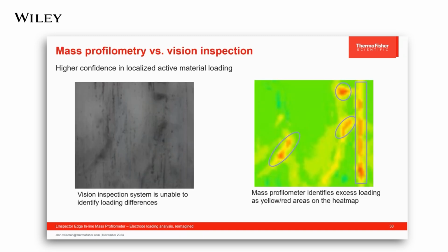The example on this slide is a good way to consider the difference between optical inspection and mass profilometry. The image from an optical inspection system on the left looks at the surface of the electrode, and in this case, the algorithm did not flag any abnormality. Mass profilometry mapping of the same sample shows clearly that the darker areas are actually areas where the loading is too high, indicated in red. Additionally, the vertical streak of high loading is clearly identifiable in the mass profilometer data, while it is completely invisible to the vision inspection system.